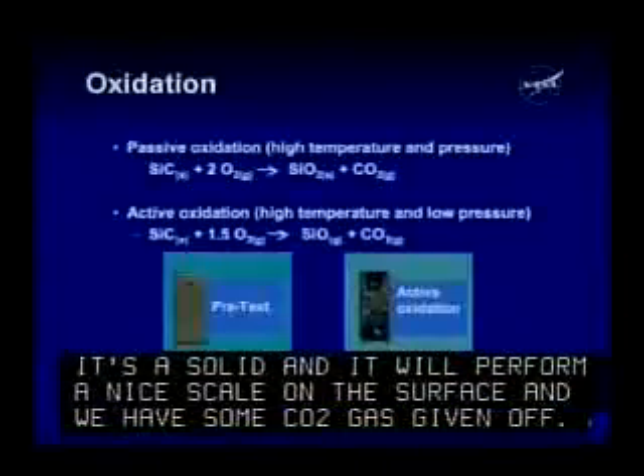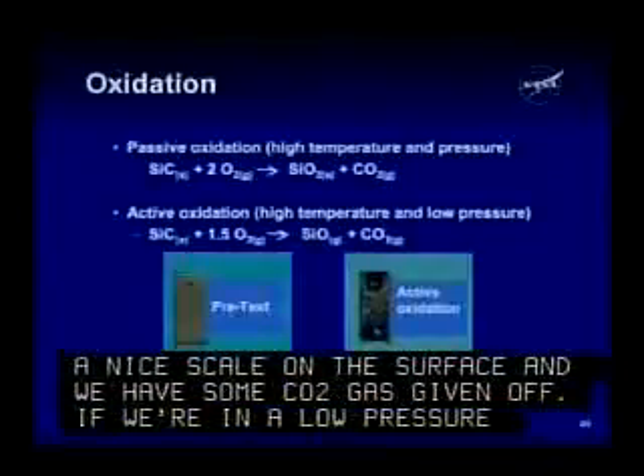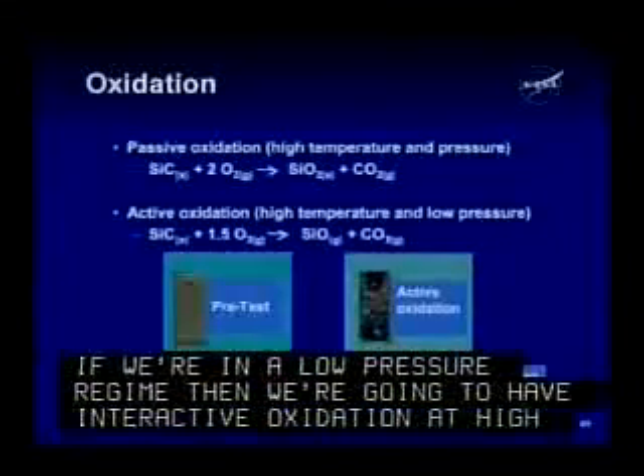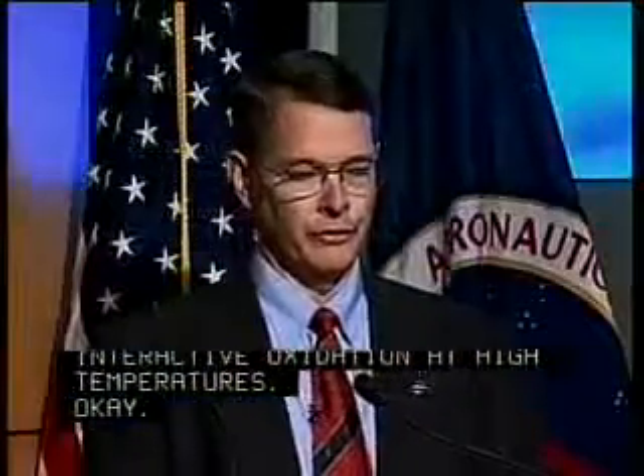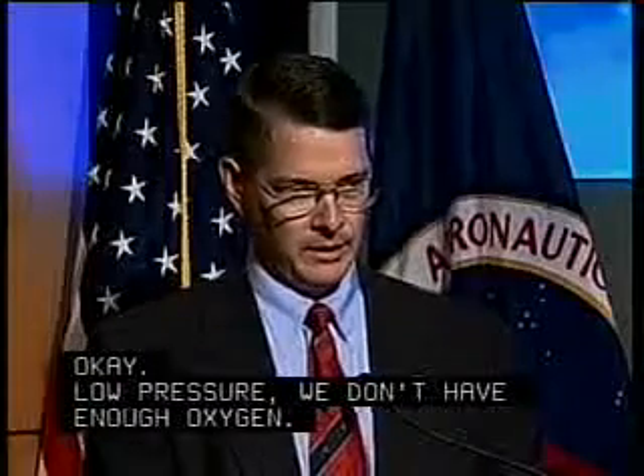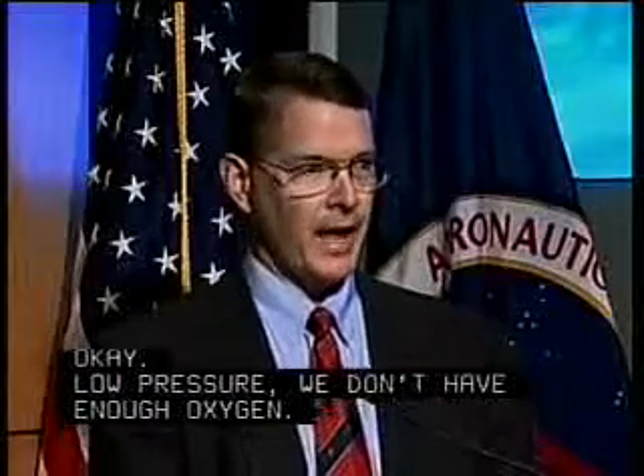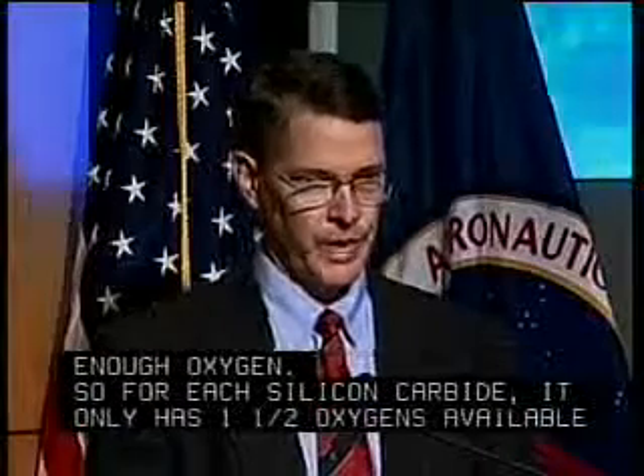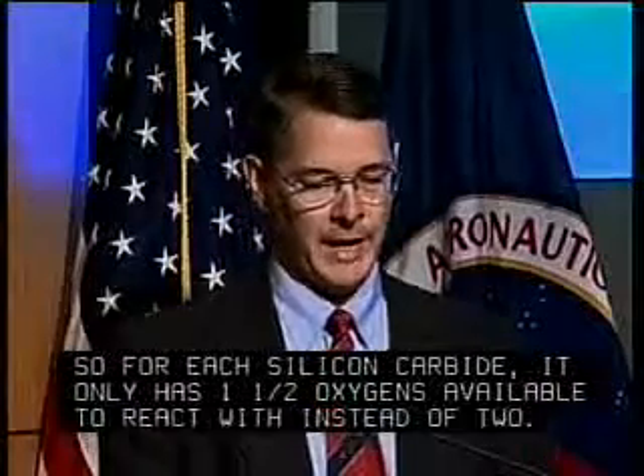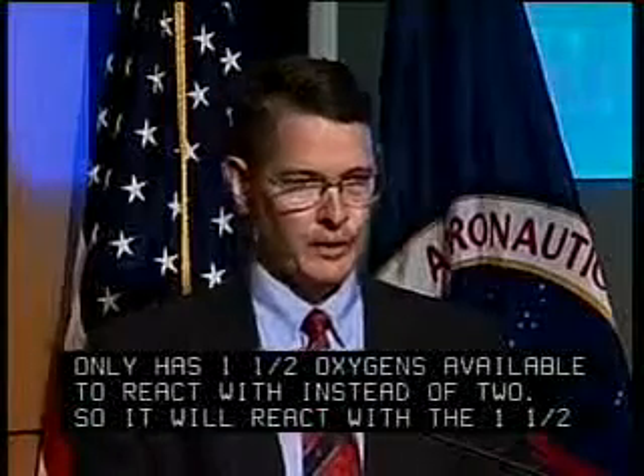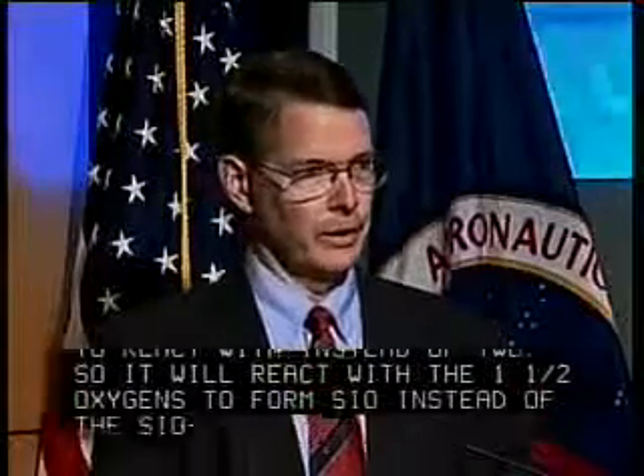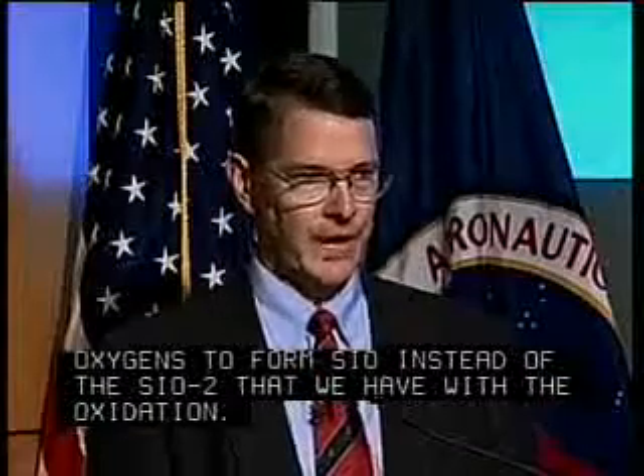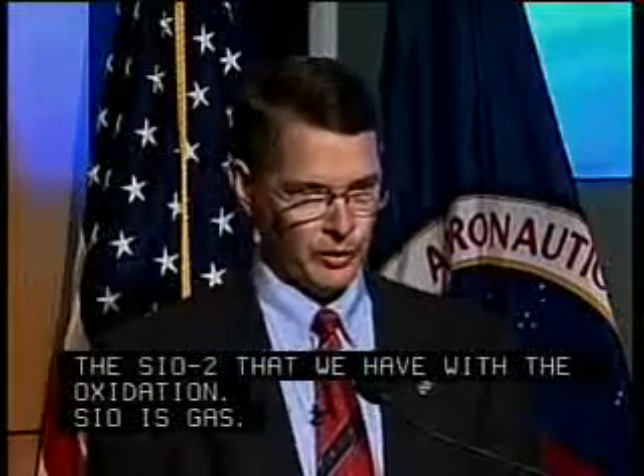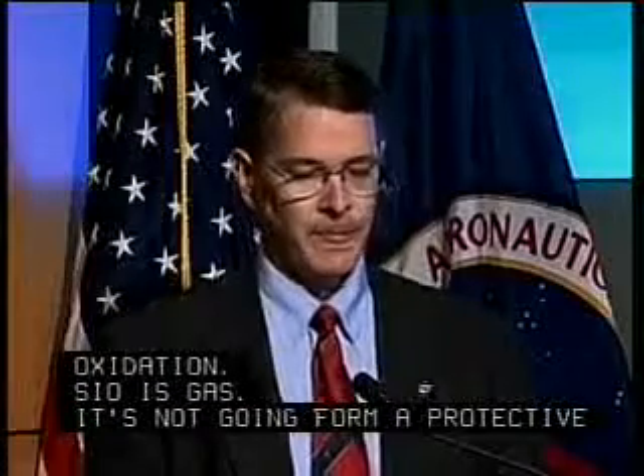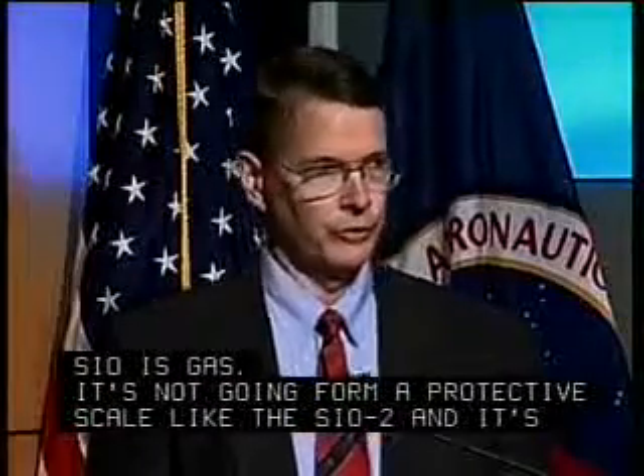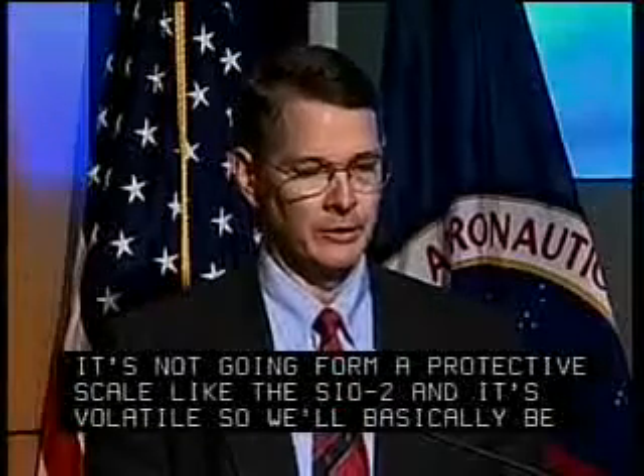If we are in a low pressure regime, then we're going to enter active oxidation at high temperatures. Okay, low pressure, we don't have enough oxygen. So for each silicon carbide, it only has 1.5 oxygens available to react with instead of 2. So it's going to react with the 1.5 oxygens to form SiO instead of the SiO2 we get when we have passive oxidation. SiO is a gas. Okay, it's not going to form a protective scale like the SiO2. And it's volatile, so we're going to basically be eating up our silicon carbide coating.